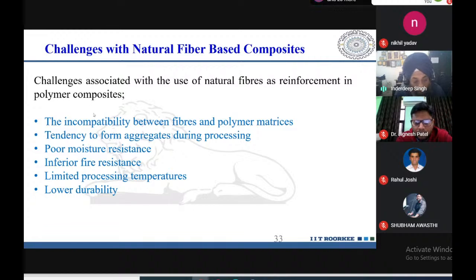Also, the next challenge is the temperatures that we can use for fabricating the composite materials. Now, that is also a big challenge, because all of you know that glass and carbon can be processed at very high temperatures, but natural fibers cannot be processed at very high temperatures. We have seen that decoloration of fibers takes place, even burning of fibers takes place at high temperatures, maybe around 400, 500 degrees centigrade. So therefore, based on the processing temperature that can be achieved for natural fibers, we have to limit certain processes.